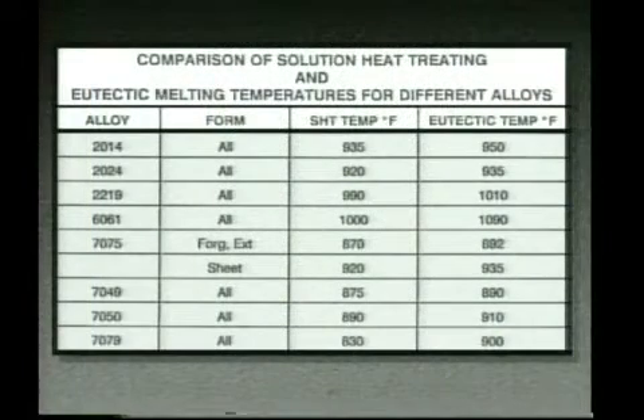The published eutectic melting temperatures, as well as the normal solution heat treating temperatures, are shown here. It can be seen that the solution heat treating temperatures are extremely close to the melting temperatures of most 2000 and 7000 series alloys.